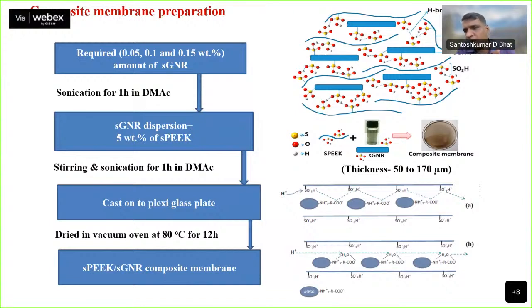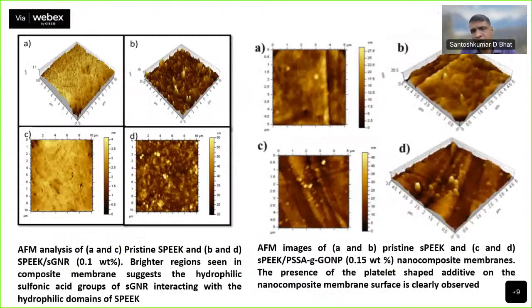So when we have the required amount of functionalized additive, you disperse it in DMAc, dimethylacetamide, and then you have a sulfonated polyether ether ketone, or sPEEK, polymer, and then you composite it, and then you place it on a plexiglass plate in a vacuum, and then you create a membrane. So once it is formed, then you can see the interaction between the additive and the membrane by various physicochemical properties. One is AFM, where we can see the distribution of the particles, nanotubes in the membrane, and another is SEM, where you can also notice the distribution of additive in the membrane.